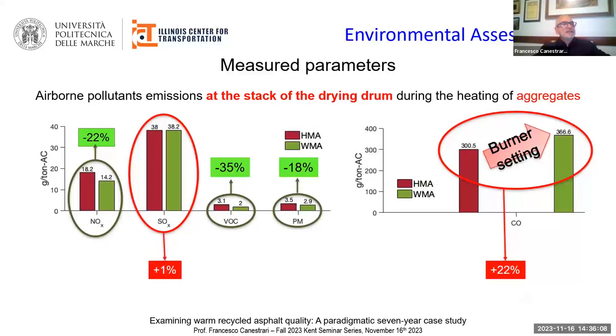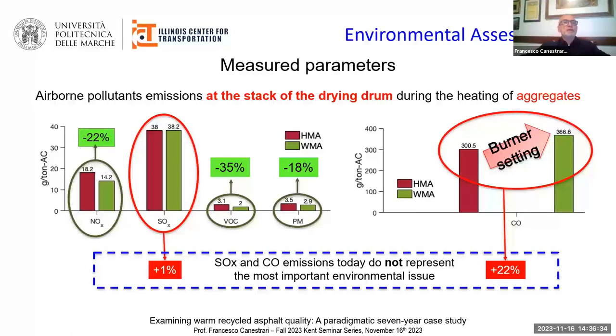During the construction of the trial section considered in this case study, airborne pollutant emissions were also measured at the stack of the drying drum during the heating of the aggregates. The results show a strong reduction in nitrogen oxides, volatile organic compounds, and particulate matter, whereas the sulfur oxides remain basically unchanged. And for carbon monoxide, an increase of 22% of emissions was found.